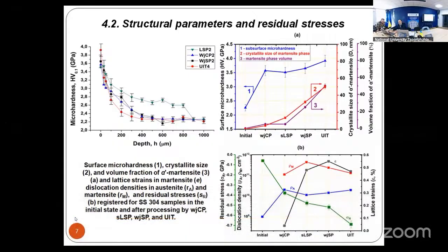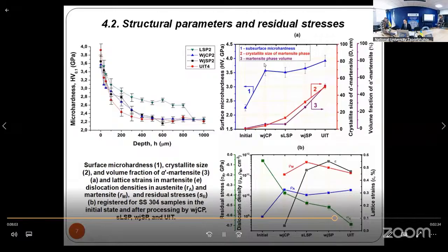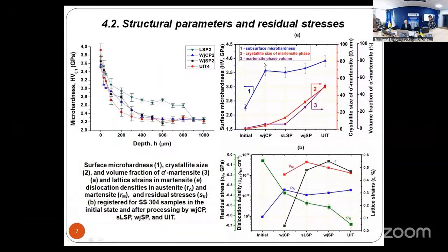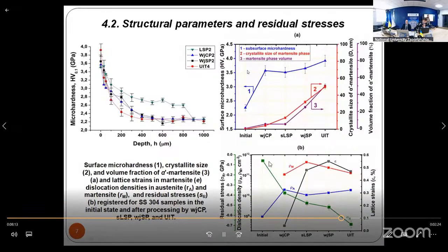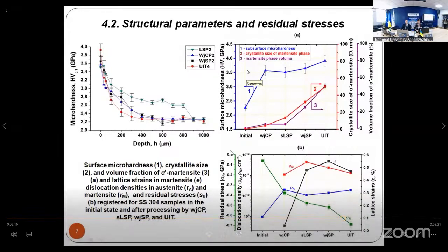As shown, the size of martensitic grains in the outermost surface layer range in a nanoscale regime due to the severe plastic deformation occurred, and it's slightly larger for the ultrasonic and wet shot process than those formed after the cavitation and laser peening techniques. The residual macro stresses were recorded; the compressive residual stresses were recorded regardless of the processing method. Here you can see the green line. It's characterized by residual stresses.